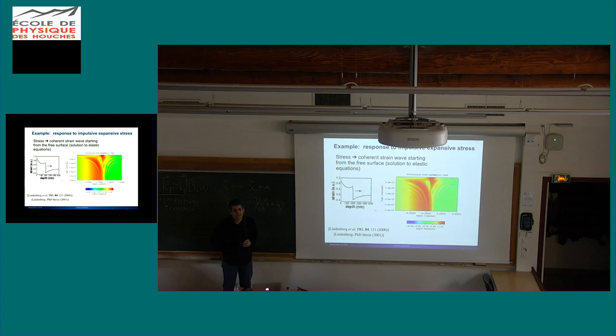Okay, now let's take more questions. If you just have static elastic scattering in whatever direction this angle corresponds to, you would see something, right? If you have a thin film, you will have a remainder of the crystal truncation rod, as long as there is some elastic field that is not trying to bend it. That should be sufficient to heterodyne. It may not be a good heterodyne. And thin films usually, if thin enough, have these ripples, finite size segments, and those will have contributions at certain angles.